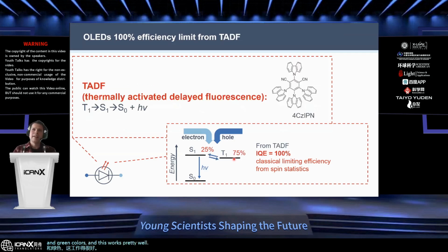And over the last decade or so, there's been a push to finding ways in which you could convert more efficient emission from triplet states through thermally activated delayed fluorescence, or E-type delayed fluorescence. And there's an interest in this area in particular because there's a long-standing issue of getting blue efficient OLEDs to work. And this is extremely important because they're making the back end of state-of-the-art displays, and this is how companies like Samsung are pushing this forward at the moment.